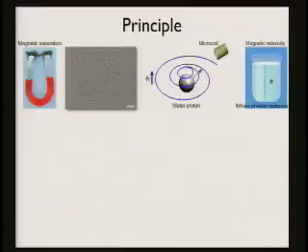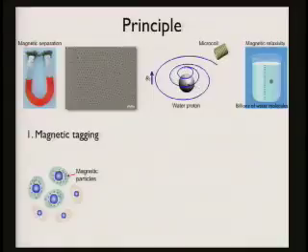Another way of looking at this is that one magnetic nanoparticle will affect billions of water molecules, and that's what we measure, i.e. there is an inherent amplification built in, billion-fold amplification. Over the years, we have developed different assay formats. The simplest assay format is magnetic tagging, where we take magnetic tags, very similar to cell separation, put antibodies on them to target them to specific cell types, to tag specific cells magnetically, and then ask how the water behaves around these to identify these cells.